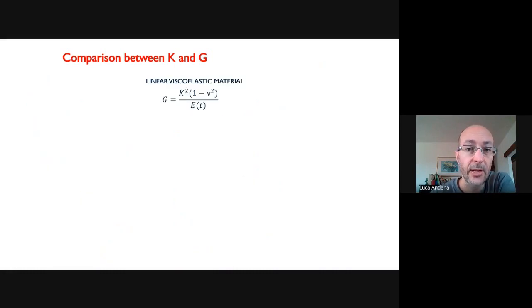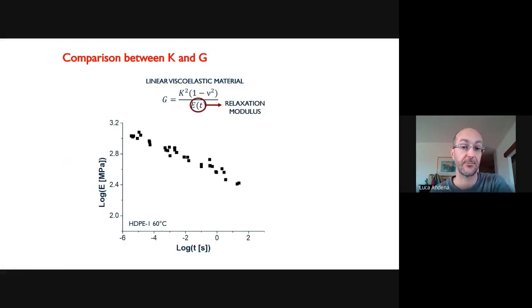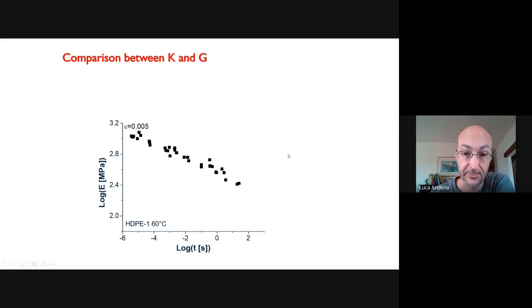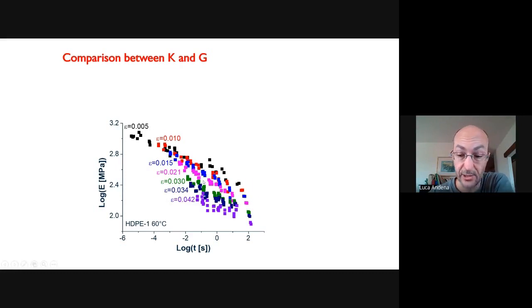However, the relationship which goes between the two uses a modulus as a way to get from G to K and vice versa. Of course, being a viscoelastic material, like many polymers, these moduli will be time dependent. You could say, okay, no worries, I will perform a relaxation experiment. You can do that and get a modulus as a function of time. The problem is that with many materials, these moduli will be strongly strain dependent because of the material nonlinearity, so that you, for example, can see that even in a range in which you are only considering a few percent of strain, you have an order of magnitude variation in the moduli.